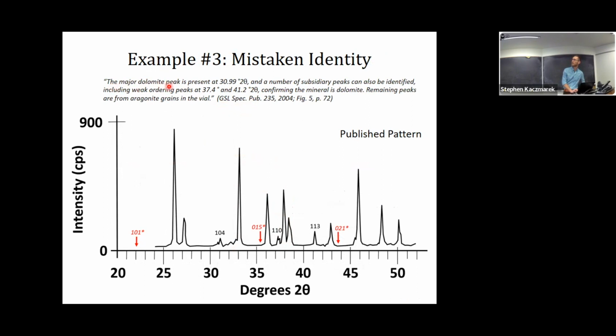It says the main dolomite peak is present at 30.99 degrees 2 theta, and a number of subsidiary peaks can also be identified, including weak ordering peaks at 37.4 degrees and 41.2, confirming the mineral's dolomite. Remaining peaks are from aragonite grains in the vial.